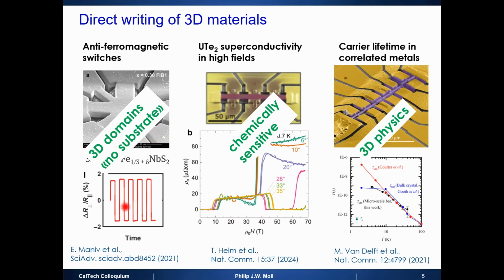So for example, the antiferromagnetic domains are very much pinned by strain and by defects in this structure. So it's very important that you don't have any stress fields that would hold them in place and you can really freely move them. UTe2 is horribly chemically sensitive. It's very, very difficult to work with. So you really need to have good control over your crystal. And in this particular case, it's really three-dimensional physics. So that's important. So I'm happy to discuss these cases in more detail.